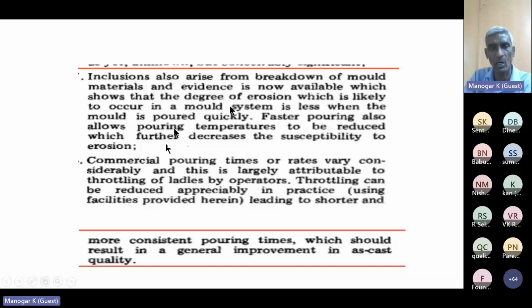Inclusion also arises from breakdown of mold. That is, the degree of erosion which is likely to occur in a mold system is less when the mold is poured quickly. Faster pouring also allows the pouring temperature to be reduced, so that you can reduce the cost and reduce the defects related to high pouring temperature. More consistent pouring time should result in a general improvement in as-cast quality.